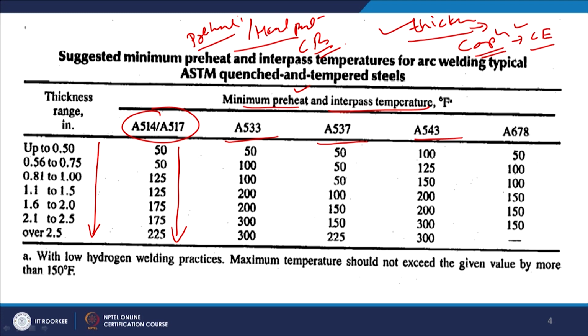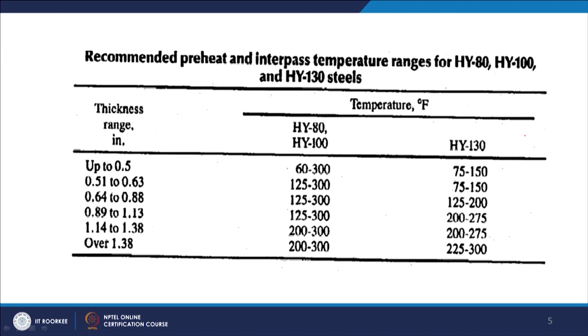So, these are the preheat and interpass temperatures for the most commonly used Q&T steels, and in the next slide we have a few more preheat and interpass temperatures for HY80, HY100 and HY130 steels. And what we notice is that in this case also, with the increase in thickness of the plate, the required preheat temperature is also increased. So almost similar preheat temperatures are there for HY80 and HY100, like for up to 0.5 inch it is 60 to 300 Fahrenheit, then 125 to 300.